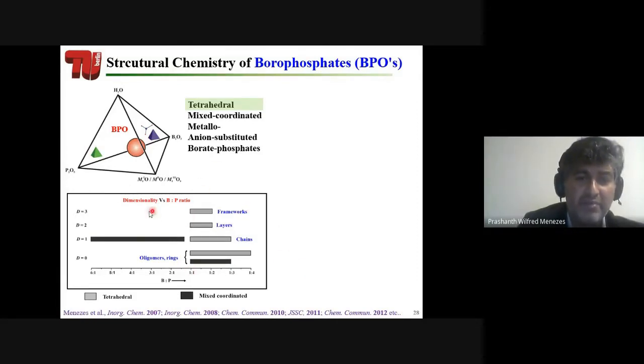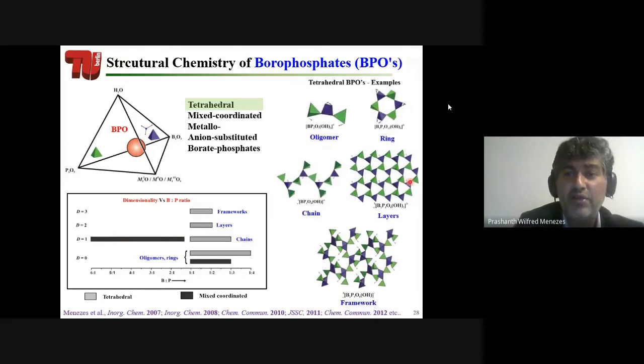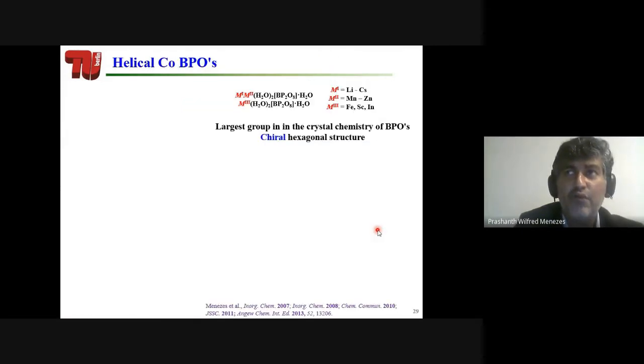Okay, so this is a chart about dimensionalities and boron phosphorus ratio. What you could see is that if you increase the phosphorus ratio, you are forming frameworks, layers, chains. And if you use a higher boron ratio, you are forming mostly mixed coordinated with chains. So how do they look? You see, this is the schematic diagram of oligomer, ring, chain, layers, and framework, and they are connected with metal octahedra to form the complete structure.